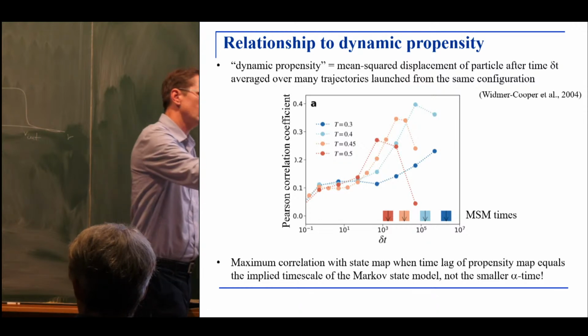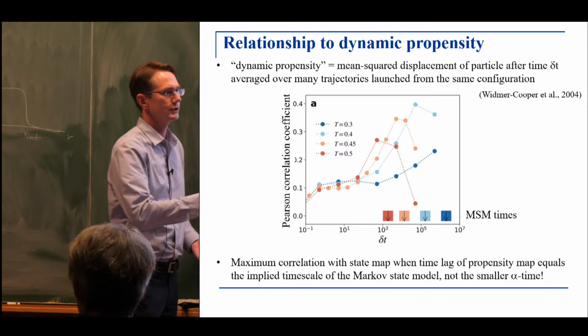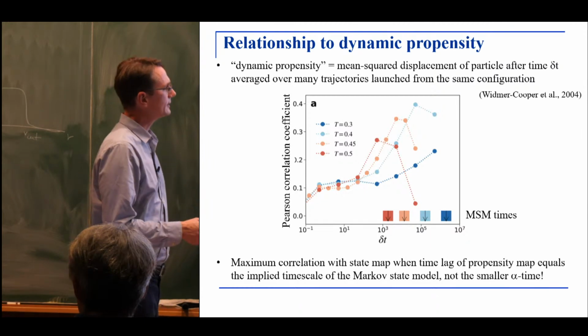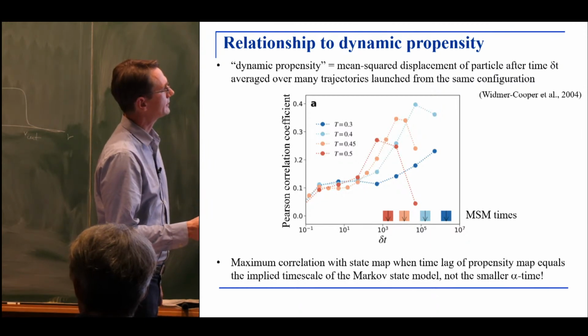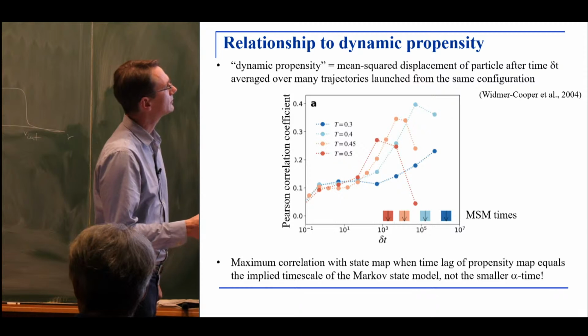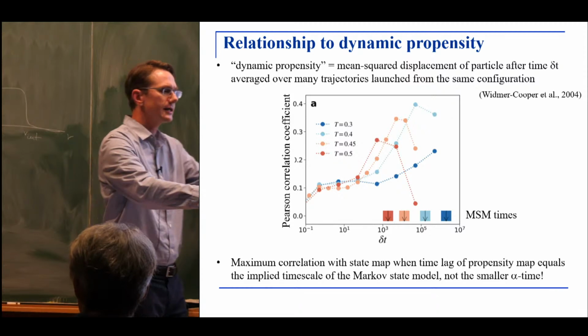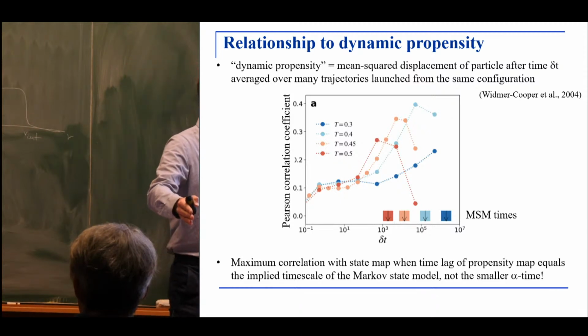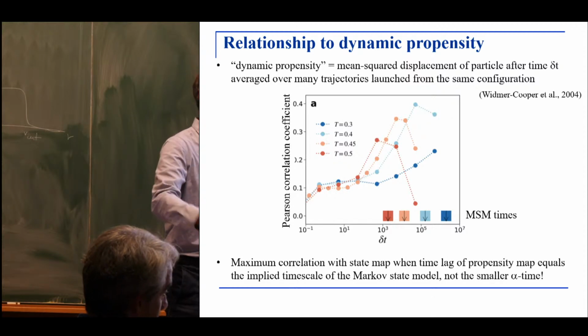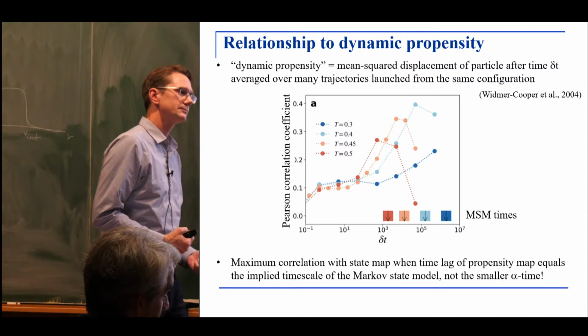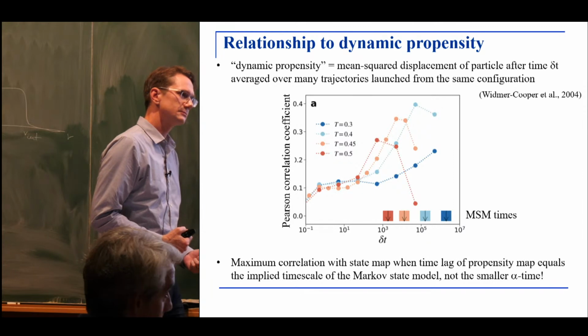The probability to observe your system in state 0 or state 1, if you wish. And so you see that this changes as a function of time and reaches a maximum when the lag time used to calculate the dynamic propensity equals this time scale that we found in the Markov state model. Does that make sense?